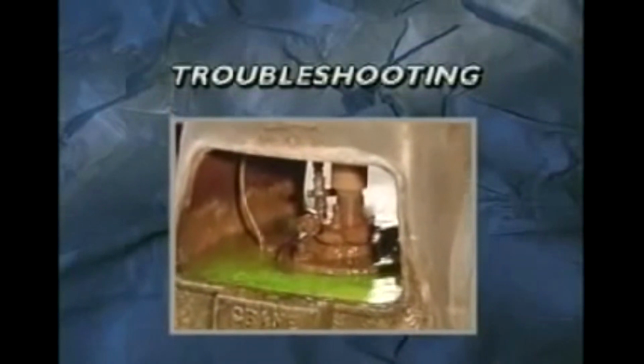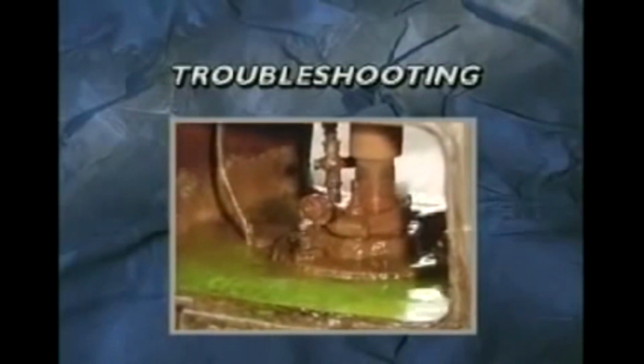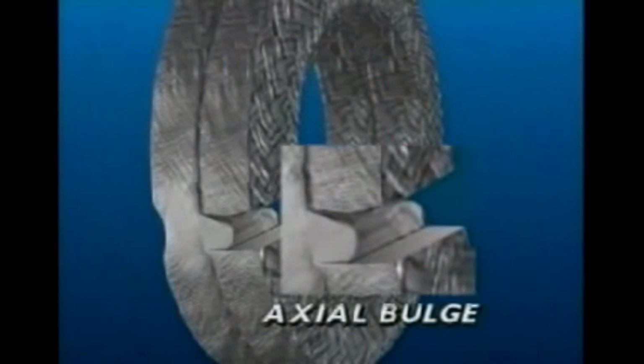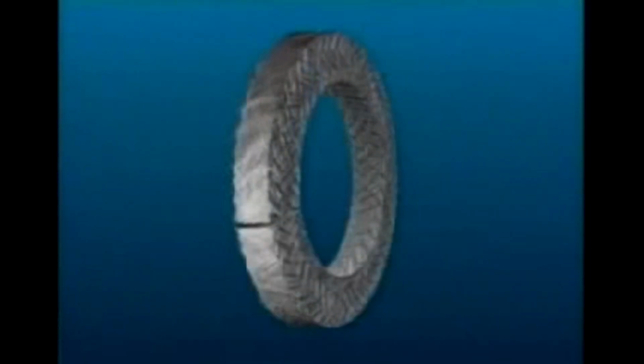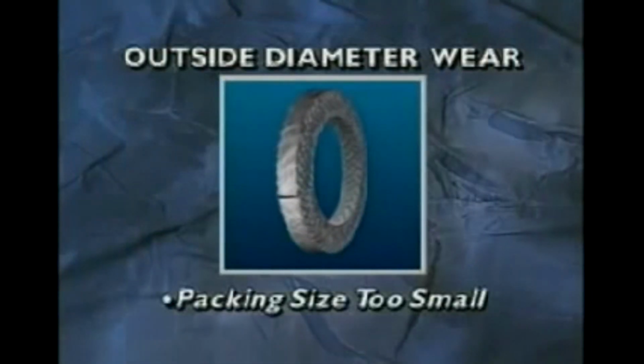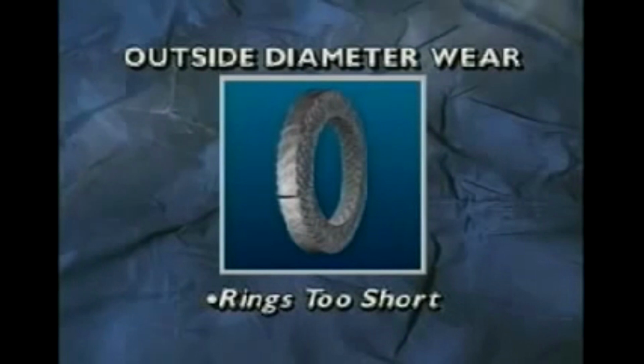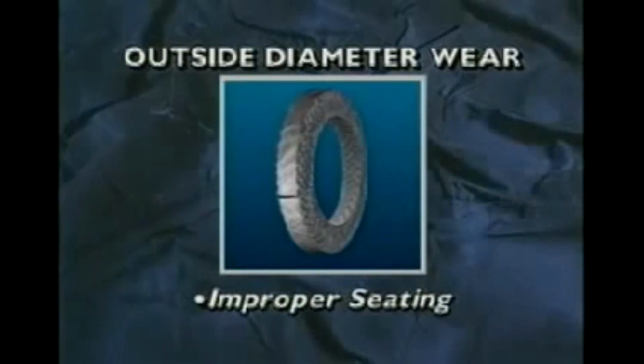If you're experiencing trouble in a pump or valve application, examining the old packing, which may also have assisted in material selection, might indicate improper procedures or mechanical problems which led to unsatisfactory performance. An axial bulge in any of the rings might indicate that the adjacent rings were cut either too short or too long. Wear on the outside of the rings is often an indication that the rings are rotating with the shaft. This may be caused by using a packing size that's too small, cutting the rings too short, or by improper seating of the rings.